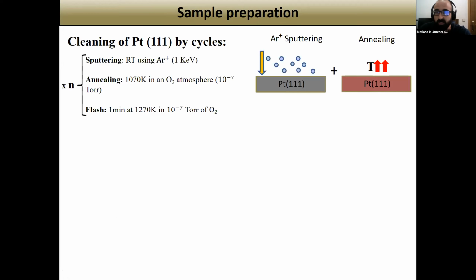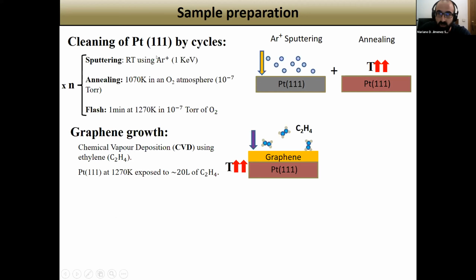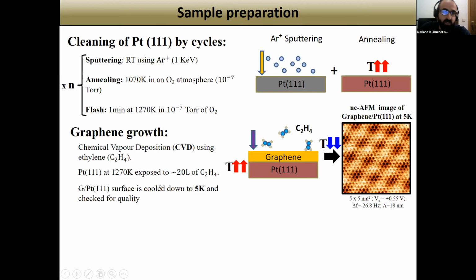Well, and what about the sample preparation? Well, the first step has been the cleaning of the platinum single crystal by means of cycles of sputtering and annealing. After that, we have grown the graphene by means of CVD of ethylene. And after this process, we have cooled down the sample to 5 Kelvin and performed measurements with the AFM in order to check the quality.